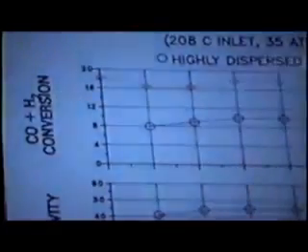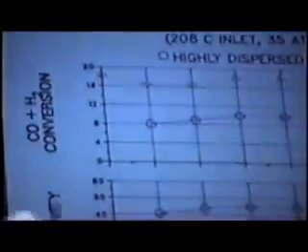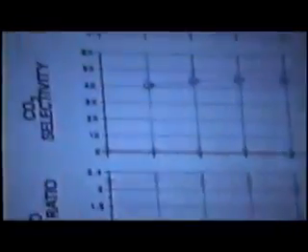This indicates that the turnover frequency is significantly higher with the 30-70 angstrom ruthenium particle catalyst, which is of no surprise. The CO2 selectivity is essentially zero with this catalyst, and the hydrogen to CO usage ratio is 2, which indicates clearly that this catalyst does not exhibit water gas shift activity.